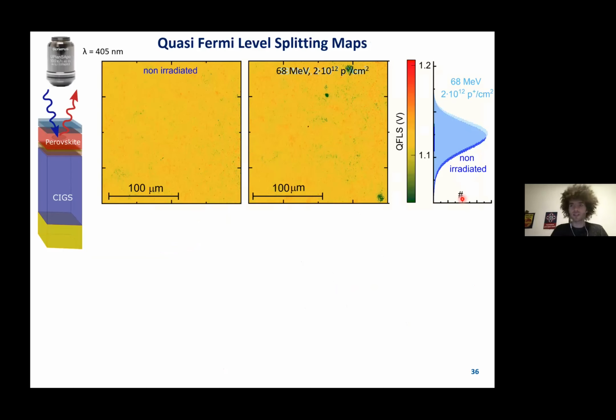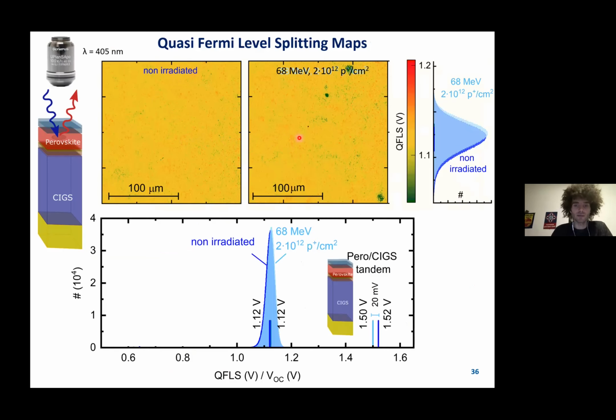All right. So again, we tried to corroborate this by PL measurements. And here I'm again showing quasi-Fermi level splitting maps calculated as before by exciting with a blue laser just the perovskite. And here we see no change whatsoever in the perovskite subcell. So the quasi-Fermi level splitting stays high, meaning we have an unchanged, identically high quality of the perovskite. And the change in VOC of the tandem is again not because of the perovskite degrading, but because of some small damage in the CIGS subcell. Still though, perovskite CIGS are a lot more radiation hard than perovskite silicon junctions.